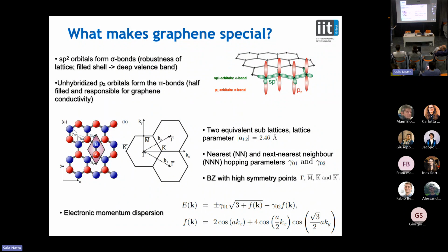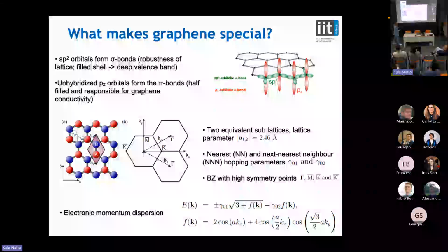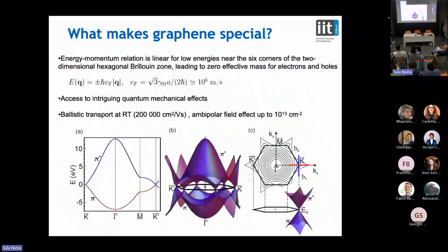Now, if we look at the carbon atom itself, we are going to have in-plane sp2 orbitals and out-of-plane pz orbitals. What makes graphene special is that we have the sigma bond, the in-plane bonds that give the mechanical resistance, and the pz, so the pi bond, that actually are half-filled and give the electrical conductivity, which is very famous for graphene. Okay, so that's basically how it is structured. Now, we will see that because of this peculiar structural characteristic, it also has a lot of interesting properties.